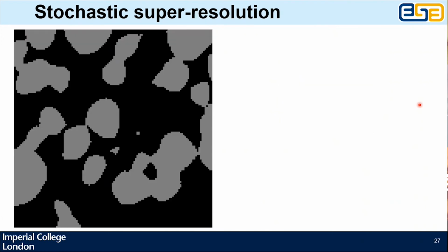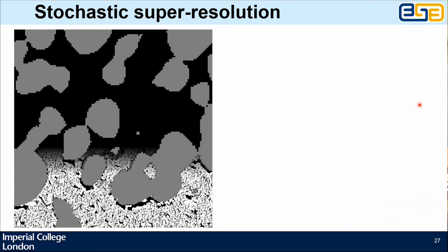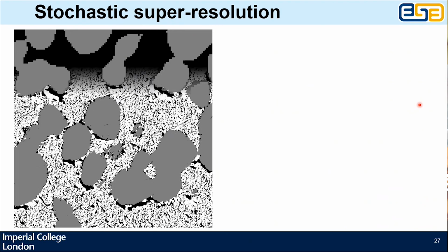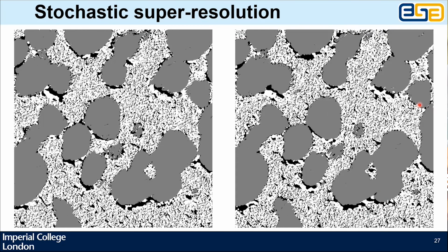So to give you a real sense close up of what's happening, if I let this run, this is a super resolution of the data, right? What you had was the underlying low res 2-phase data, and I've now super resolved it, and it's got these 3 phases with the details. But I'm still passing my generator, the generator of my GAN, not just the low res information as a map, but also some random noise. There is still a random seed, this latent vector, which means that for any given low res image, there are many different incarnations of the high-res version that it could generate.